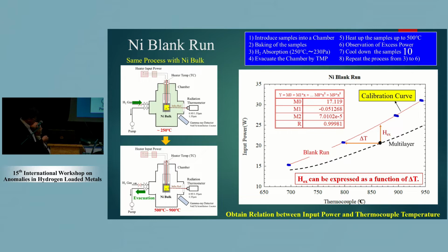So we use a blank run. This kind of calibration curve we get. For the blank run here, it's for nickel bulk only. This one is multi-layer nickel bulk and multi-layer curve here. So for example, if we input 20 watt, we get 800 degrees centigrade, for example.